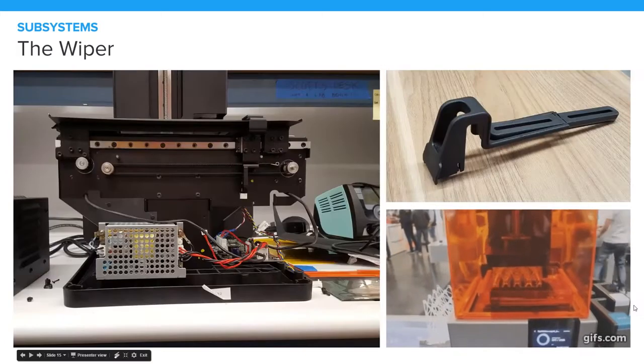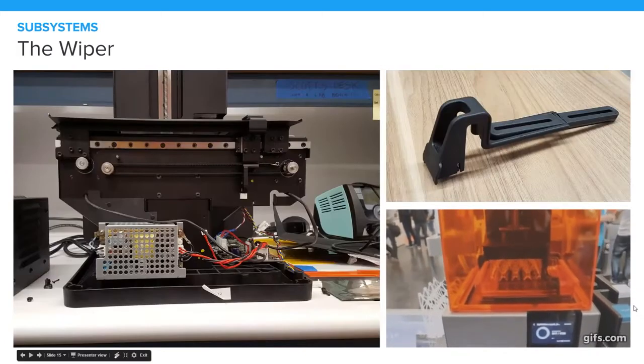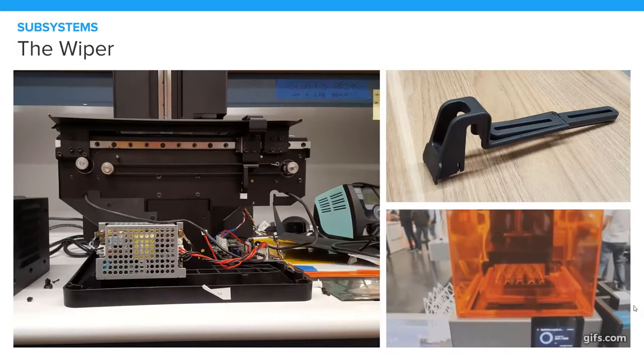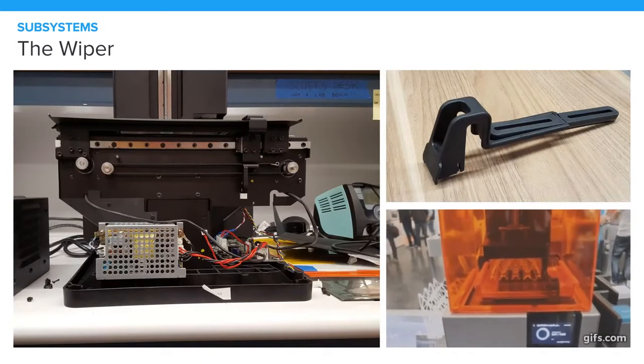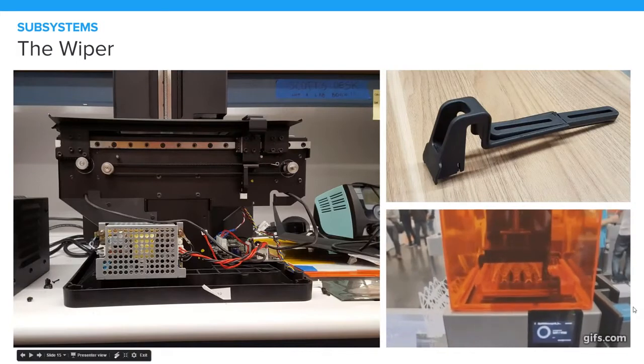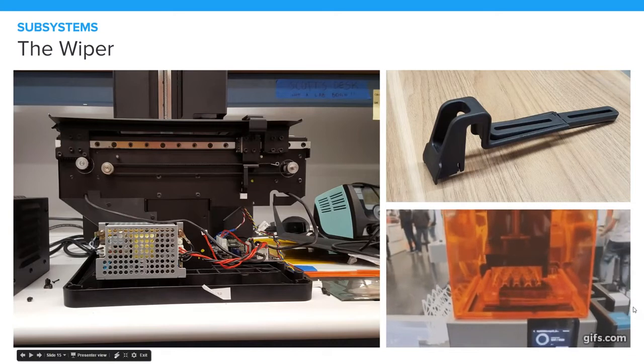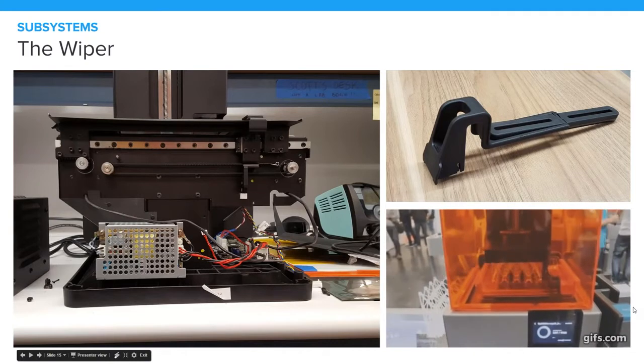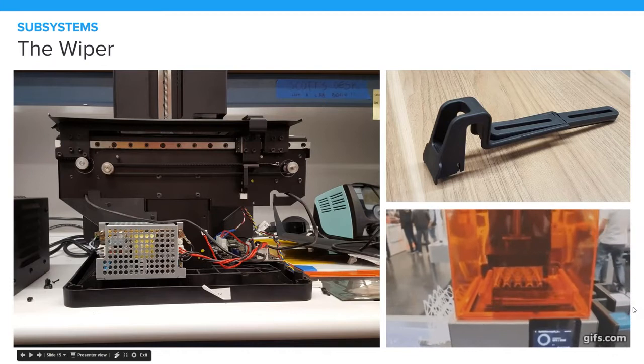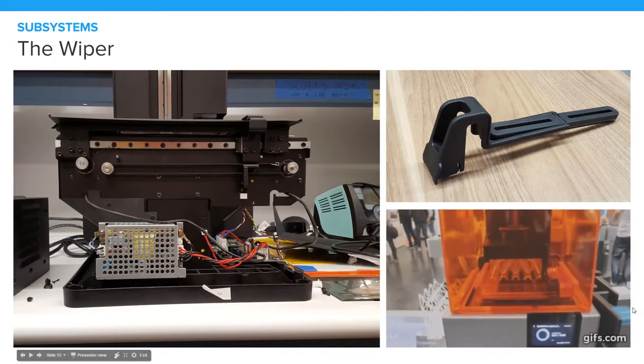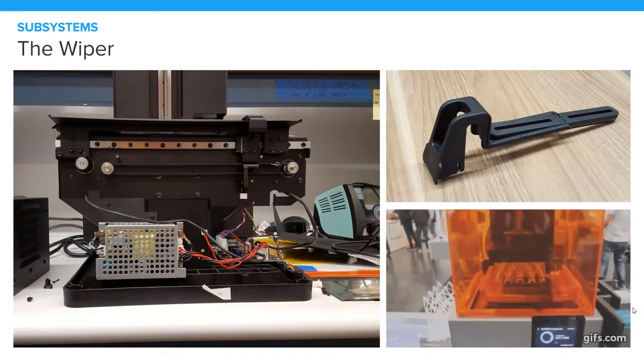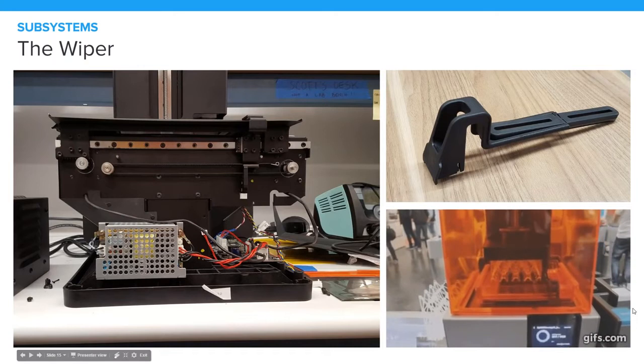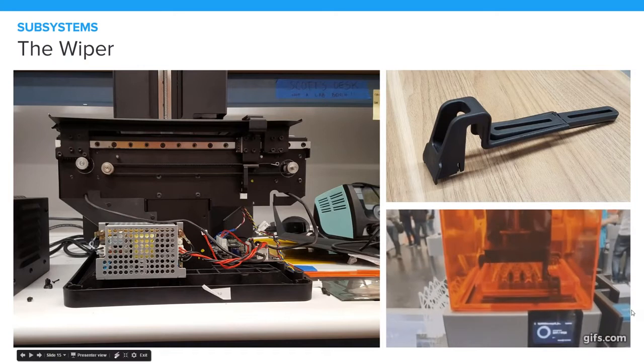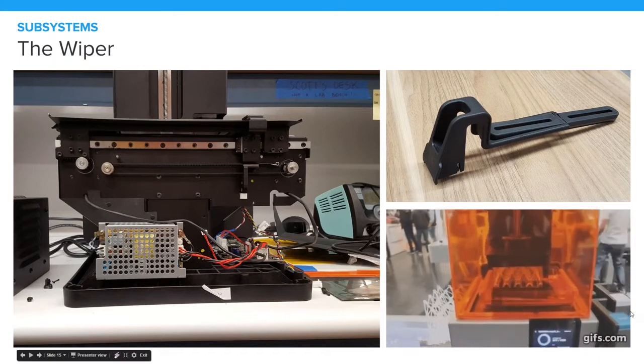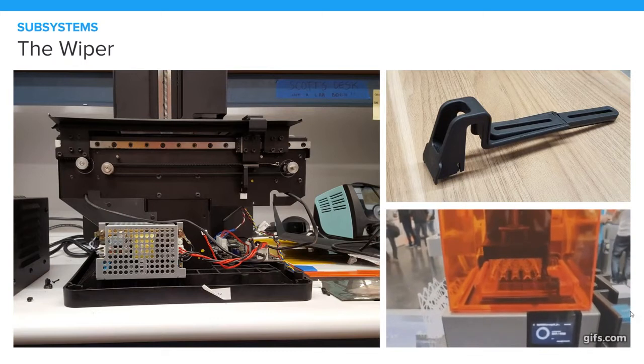So without complicating things too much, we also decided to add a wiper. We didn't do it without a reason. The basic purpose of the wiper is to stir up the resin and oxygenate the PDMS layer. I just said a lot of letters. PDMS stands for polydimethylsiloxane. I'm not sure if that helps. It's basically silicone at the bottom of the tank, and it's fairly inert. It holds oxygen well, and it's somewhat flexible, so it can handle any perturbations caused by the peel operation.